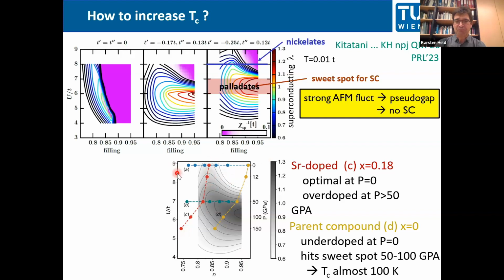So without any pressure, 18% was the sweet spot for superconductivity. So it was experimentally the maximal Tc. But if you dope it now, the electron pockets grow, you get more and more holes even, so you stick with 18% strontium doping, and you go to the overdoped region. For the parent compound, instead, we were hugely underdoped without any pressure. But now applying pressure brings us to the 7% doping at 50 gigapascal, and then we cross the region where you have the maximal Tc. And therefore, you get a maximal Tc at around 50 to 100 gigapascal.